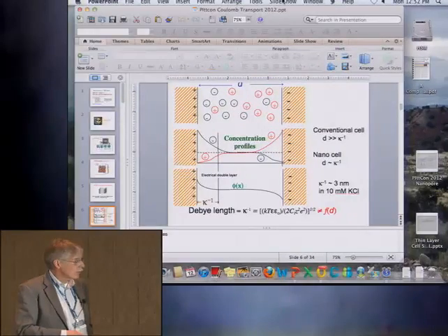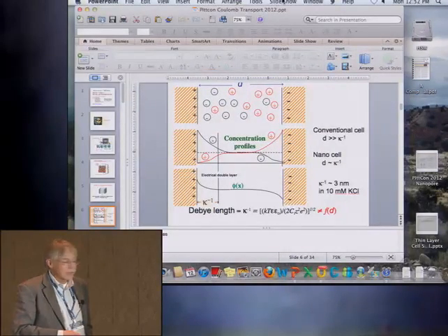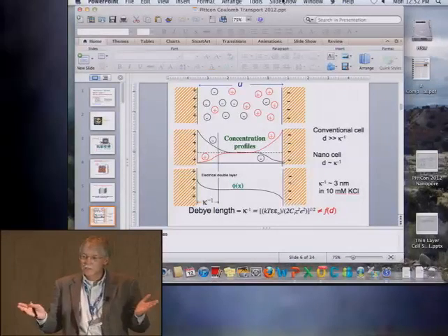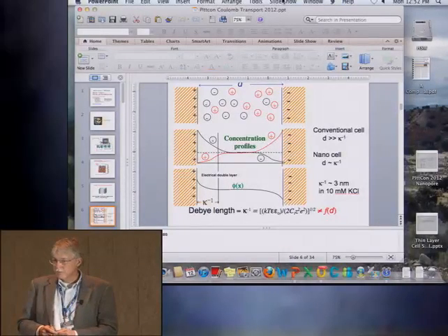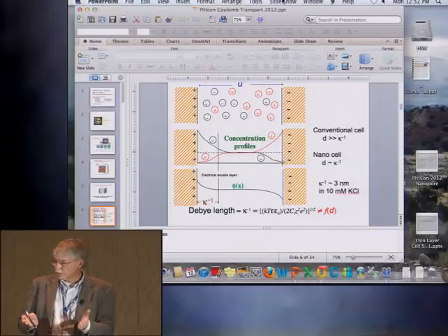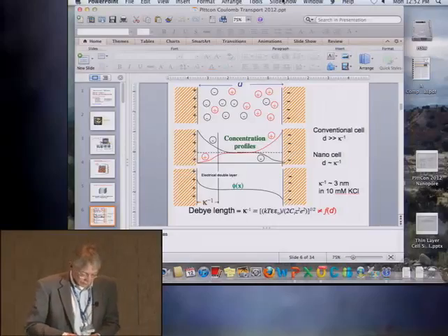And when the thickness of the cell is much larger than the Debye length, then you just have ordinary electrochemistry, 2 electrodes separated by infinity for all practical purposes. But if you can push the electrodes together, and just to calibrate you, the Debye length in 10 millimolar KCl is 3 nanometers. So if you can push these electrodes, say within 20 nanometers of each other, they should sense each other in terms of the electrostatic potential. And that's going to affect the transport, but it's also going to affect the kinetics, electron transfer kinetics, or ion transfer kinetics at the interfaces.